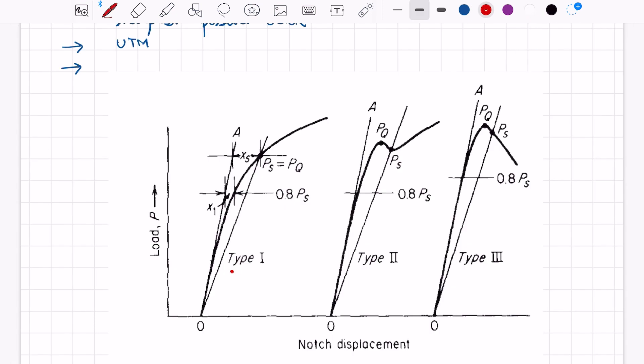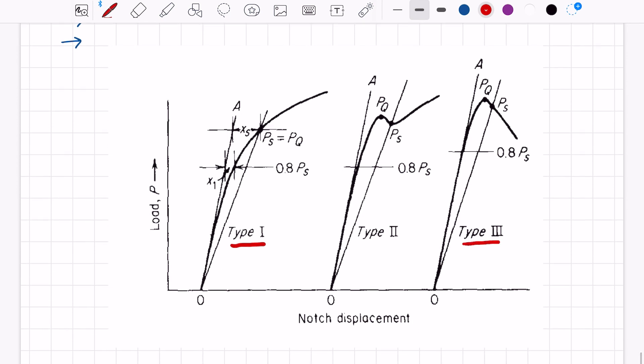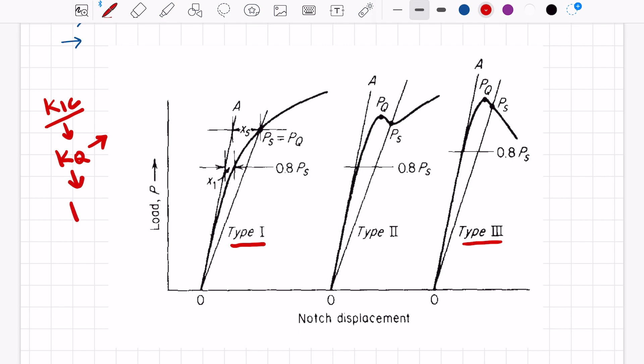The Type 1 curve is obtained when a ductile metal is tested. The Type 3 curve is obtained when a very brittle elastic material is tested. In order to obtain a valid K1C value, a few rules have to be followed as present in ASTM E399 standard. First, a conditional value of fracture toughness, denoted by KQ, has to be determined. To determine KQ, we need the PQ value — the conditional value of load.